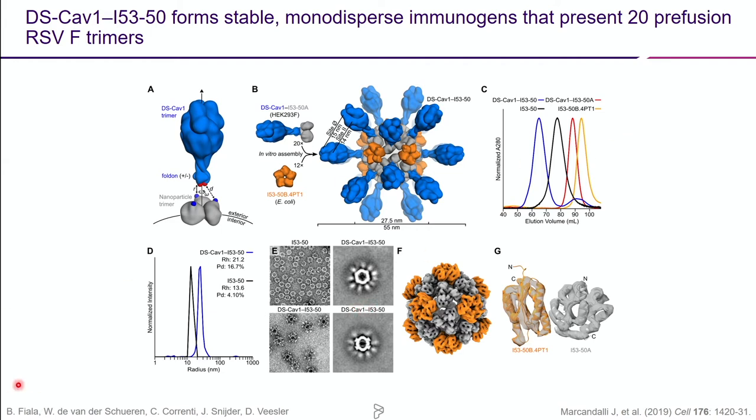So we do extensive quality control on these to make sure that the particles are nicely formed, they're not aggregating, et cetera, et cetera. And you'll notice that when we average particles by electron microscopy, the antigen kind of blurs out. It gets a little bit blurry. And that's because we used a flexible genetic linker to link the antigen to the underlying nanoparticle. So it really is kind of waving around. It's an open question what effect that has on the immunogenicity of the vaccine. It's something we're exploring now through design. But when David Veesler here in the biochemistry department solved a single particle reconstruction of this nanoparticle by cryo-EM, he couldn't even see the antigen, he just saw the nanoparticle core.